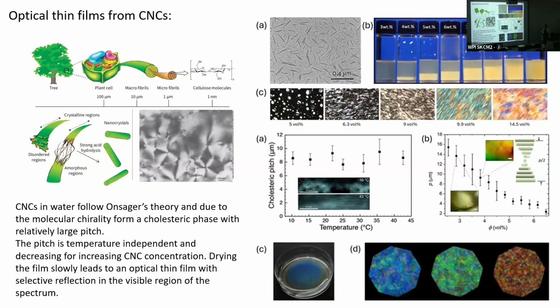This will make a cholesteric structure because, as we said, cellulose is polymerized sugar. All the sugars are chiral; they're right-handed, and the helix they make is left-handed. But that's why I'm saying that from the configuration of the molecule, you could not say what kind of helix they make. But all the sugars make left-handed helixes.